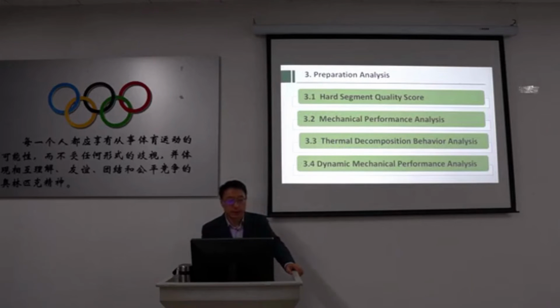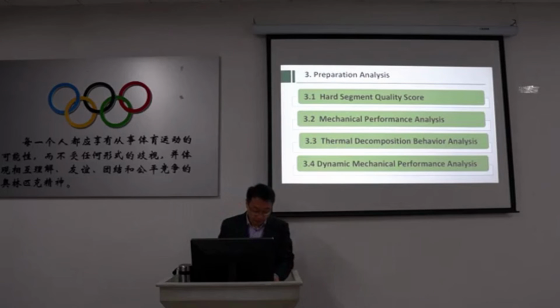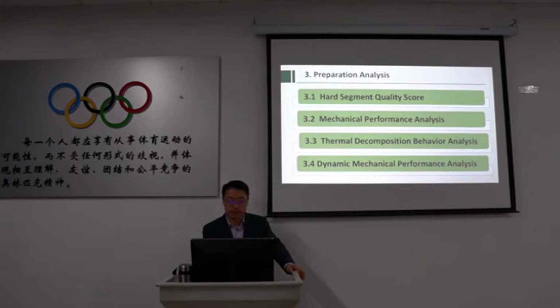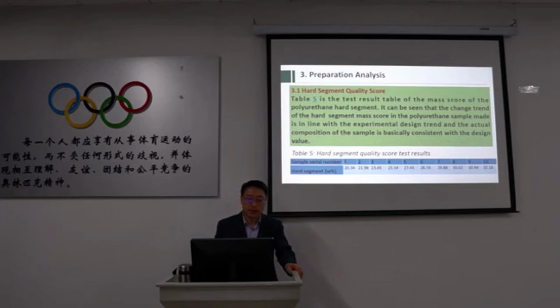Part 3. Experimental preparation analysis. Experimental analysis includes hard segment quality score, mechanical performance analysis, thermal decomposition behavior analysis, and dynamic mechanical performance analysis. 3.1 Hard segment quality score. Table 5 is the test result table of the mass fraction of the polyurethane hard segment. It can be seen that the trend of the hard segment mass fraction in the polyurethane sample made is in line with the experimental design trend, and the actual composition of the sample is basically consistent with the design value.